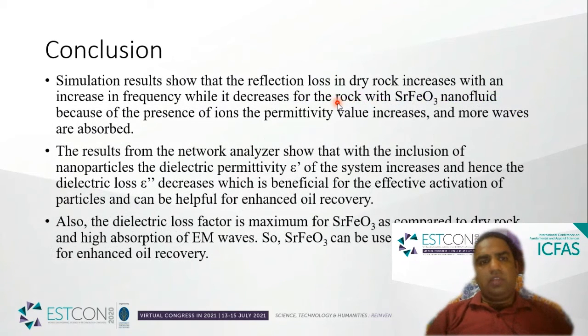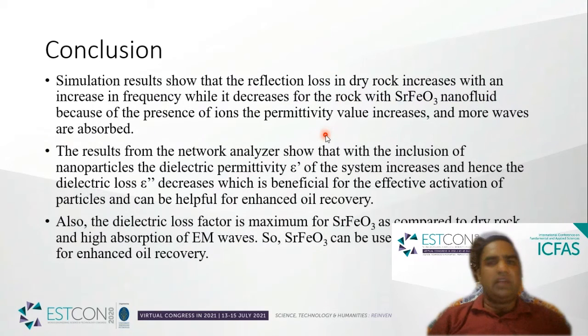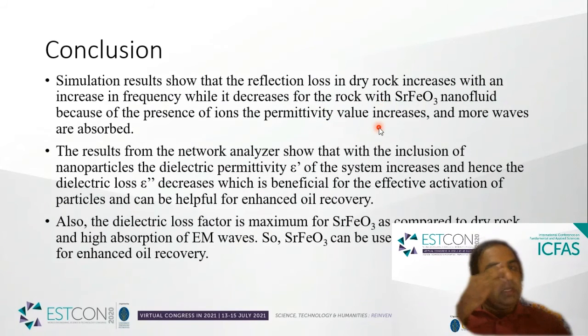So for the conclusion, our simulation results show that the reflection loss in the dry rock increases with an increase in the frequency, while it decreases for the rock with strontium ferrite nanofluid. This is due to the presence of ions, the permittivity value increases, and more waves are absorbed for strontium ferrite.